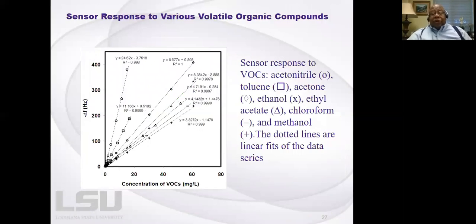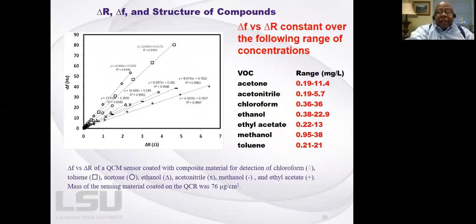So here's what he observed, where he looked at the change in frequency as a function of different materials. He said the slope was very much dependent on the material used. I said, that's very interesting. And he said, I wonder why. I said, I don't know why, but let's try this. Let's try plotting these kinds of materials, and we're going to plot delta F versus delta R. And again, he noticed that the slope of delta F versus delta R was very much dependent on the material that you use in the gas phase that you're detecting.